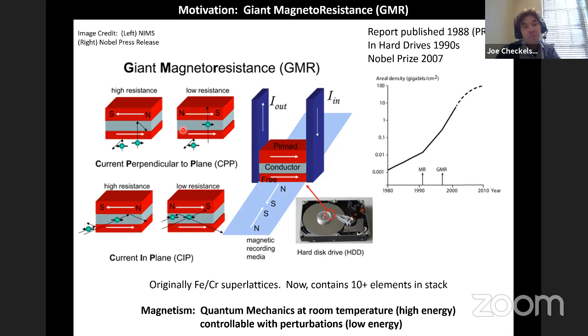And how this further leveraged magnetism was the realization that these magnetic structures are very robust. If you make them out of the right materials, they can be magnetic at far above room temperature. But because of that acute sensitivity to external magnetic fields I referred to before, you could bring this little structure down near, for example, a strip of little magnetic bits and use it to sense the local magnetic orientation, because this so-called free layer could flip in the presence of the local magnetic bit, and then you could detect that electrically by seeing the change in resistance, right? So this seemingly simple concept was actually a very deep breakthrough.